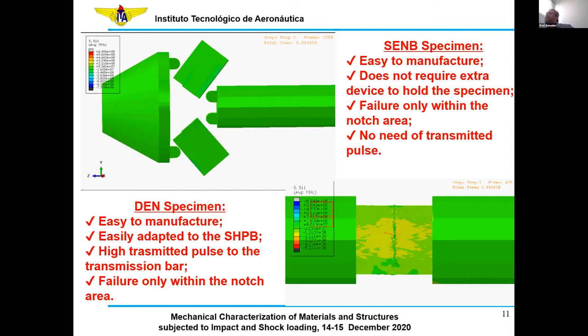Here I have listed some of the advantages of these specimen configurations. If we look, for instance, at the single edge notch bending specimen, it's a very easy specimen to manufacture. It does not require any extra device to hold the specimen in the bar. And if well designed, we ensure that the failure occurs only within the notched area, which is a desirable feature for this test. Another good point about this specimen configuration is that there is no need for the transmitted pulse. We just need the incident pulse to obtain the intralaminar fracture toughness.